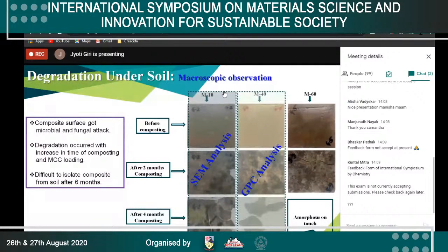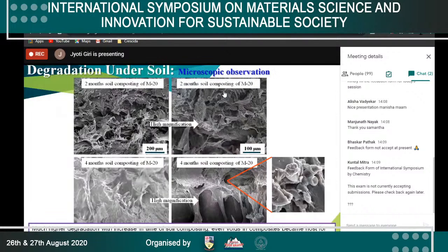6 months. In this micrograph, we can see that lots of voids are forming at the place of the MCC. With the time spent in the soil, the composites show polymer degradation, which adheres to the MCC as well. With that, the void size is also increasing, where microbial colony growth was also observed.